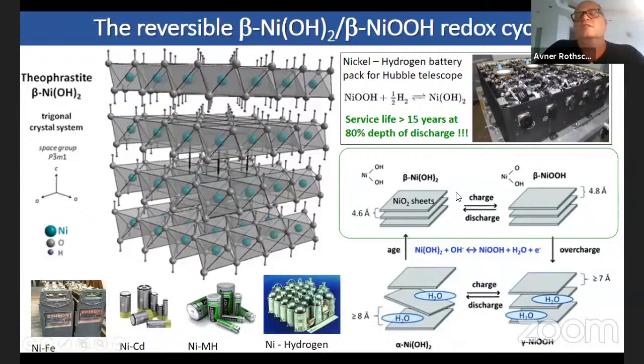So in the nickel hydroxide system, there are 4 phases. 2 of them, the cycling between them is cyclable. That's the beta nickel hydroxide, beta nickel oxyhydroxide. We don't want to reach the alpha and gamma phases because the interlamellar spacing between them changes upon cycling. So we limit ourselves to the beta-beta cycle, and the way to do this is by monitoring the potential as